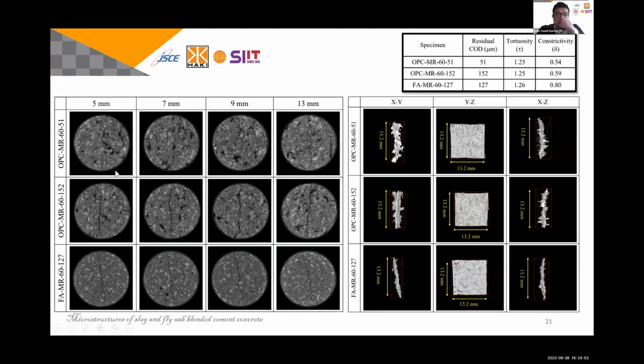As you can see here, this is the crack geometry. We have 3 samples. First, OPC with lower crack opening width, here 51 micrometer. The second one, OPC with 152 micrometer, and the last we have a fly ash specimen with 127. This is the image from 5 millimeter, 7 millimeter, 9 millimeter, and 13 millimeter from bottom to top.